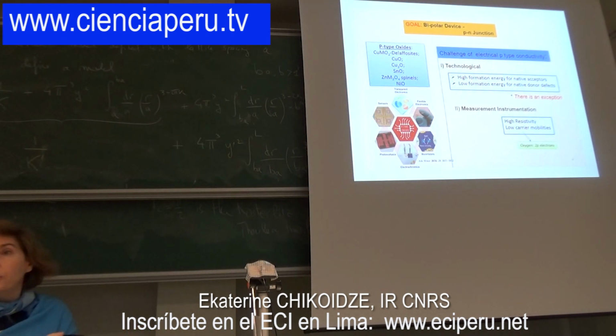But still much effort has been made to get P-type oxides, and here I listed some of them which have already been demonstrated as P-type: the family of delafossides, for example strontium copper oxide and aluminium copper oxide. There is a family of delafosside oxides which have P-type conductivity, but the problem is the mobility is very, very low. Cuprous oxide is a classical P-type oxide, SnO, the family of spinel structure oxides has been discovered as P-type, and the very famous nickel oxide.